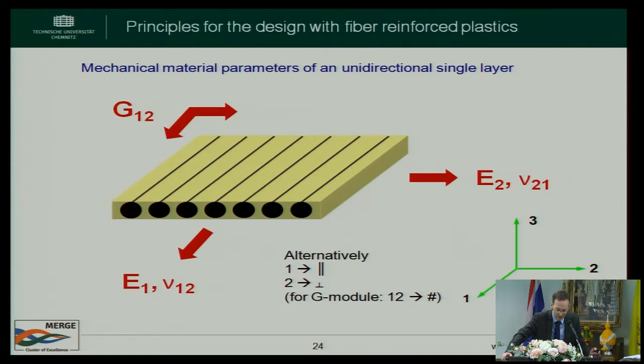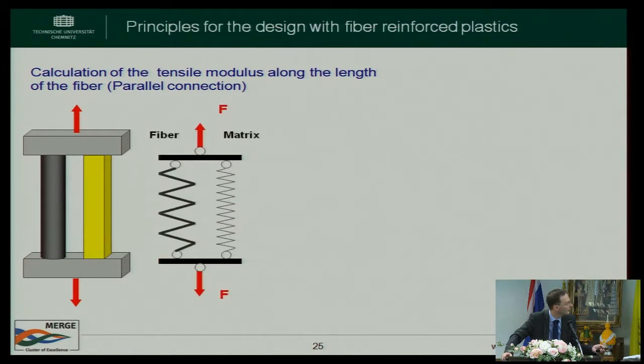Now, for our fiber reinforced plastics, as you can see here, let's say we have some, which is black, made here, the fibers, single carbon fibers embedded in some yellow matrix. We have one tensile modulus in fiber direction. We have another tensile modulus perpendicular to fiber direction. And here we have one shear modulus. Also we have two different Poisson ratios. Nothing I want to go too much in details, but especially tensile modulus in fiber direction and tensile modulus perpendicular to fiber direction is totally different. And this is only for calculation.